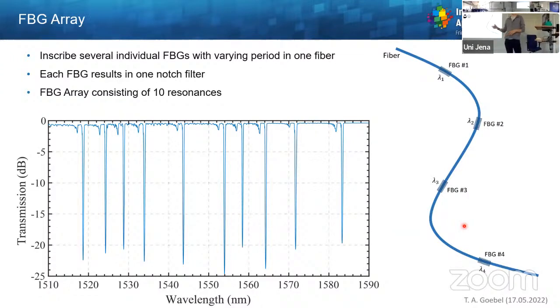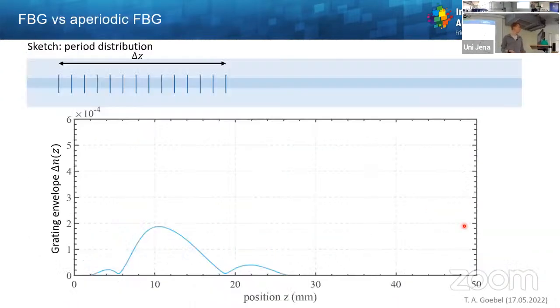However, as we have now 10 individual gratings, this gets a bit interesting in stabilizing these, because as you have heard in the talk before, they are very sensitive to strain or temperature changes. So if you want to use them as a filter device, you need to stabilize the wavelengths, otherwise they would move around and don't filter our light. So if we have 10 resonances, we need somehow 10 packages to make everything more stable. So this limits a bit the capability of inscribing individual gratings into the fiber. And also it makes it quite large, because this is what I want to show you next. This is the refractive index change in our fiber core.